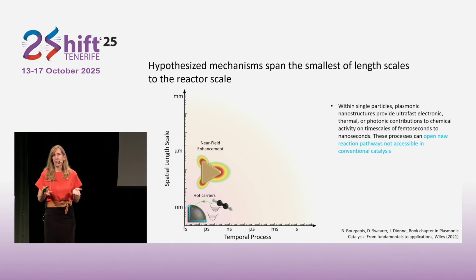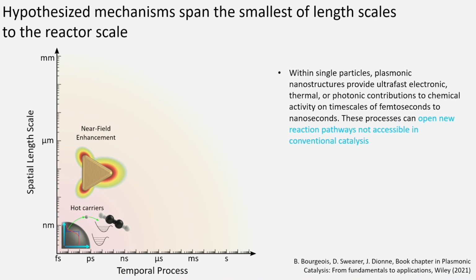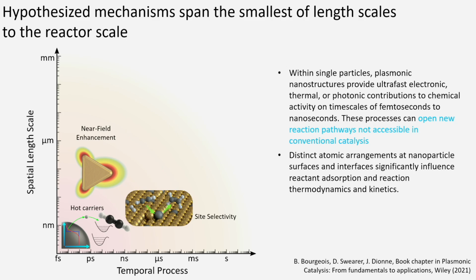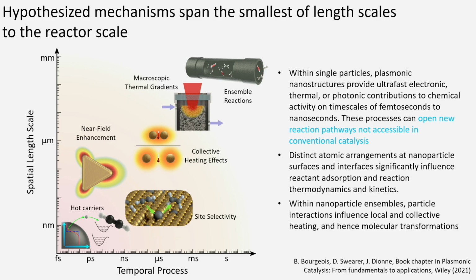Then, of course, you have the near-field enhancement, the increased local density of optical states that can give rise to modified electronic energy levels, modified thermal energy levels. And that all has to get mapped onto site selectivity. So intrinsically, what are the sites that are most active for catalysis on the particular catalytic particle you have? And then we're not just looking at these catalysts in isolation. You are putting them into reactors with a certain mass loading. So you have to think about how the catalytic nanoparticles are interacting with each other to give rise to collective heating effects, and how that heating plus whatever optical illumination you have might be propagating throughout the entire reactor bed, which can range anywhere from a benchtop reactor to something like that city skyscraper that I showed you earlier in the presentation, where you have like a 10-story building that is your reactor.